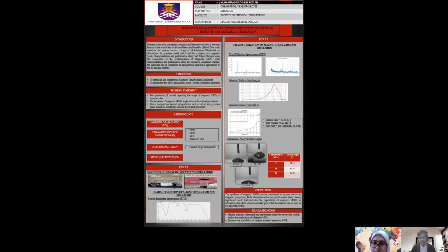You mentioned that a higher concentration of MOS2 lowers the contact angle. You want the lowest contact angle possible, is it? Yes. But if you add 100%, what is going to happen to the contact angle? Is it going to become zero? No. In wettability alteration, the lowest contact angle is not always the best that we need. We need to manipulate the concentration to suit the permeability of the reservoir.